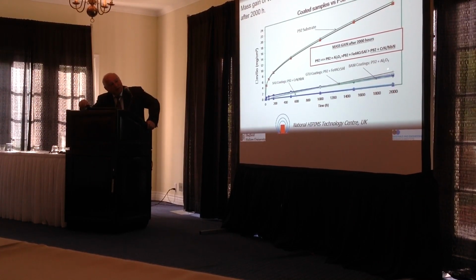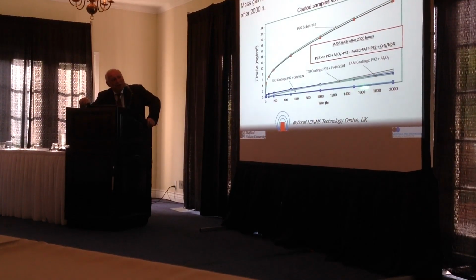And these are coatings, actually this one is an 80 micron thick coating, which is a very complicated alloy. And this is a coating produced by BAM, which is an oxide layer, so we were surprised that we can actually outperform this type of materials with our coating.